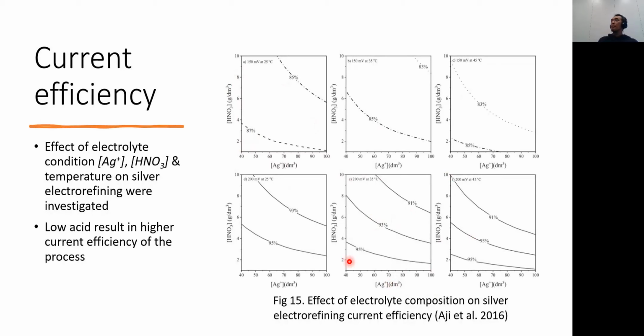Why is this happening? Because there is a special mechanism for silver dissolution in nitric acid medium. The nitrate, NO3 minus ions, have this self-catalytic phenomenon. The ions from both the free acid and the silver nitrate used to make this electrolyte have this autocatalytic process to dissolve the pure silver at the bottom of the cells. That's why the concentrations of both nitric acid and silver need to be kept as low as possible, from these findings.